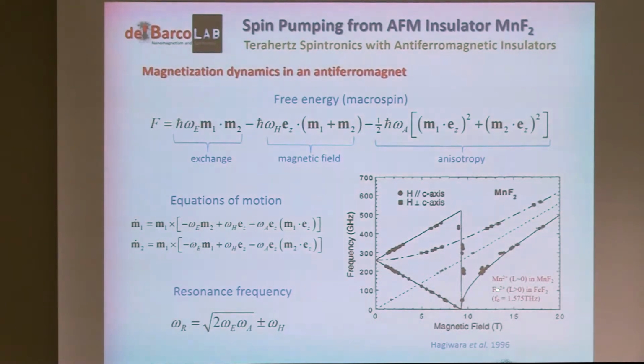But if you replace the manganese by iron, where the angular momentum is important, then you can drive the resonance into 1.6, and then other antiferromagnets have other frequencies. So you can play with that. And then, of course, as soon as you apply a magnetic field, you will split the degenerate modes into two different energies, right? And at some point, you will reach the spin flip-flop transition where both sublattices will align in the direction of the magnetic field, and then things will change.